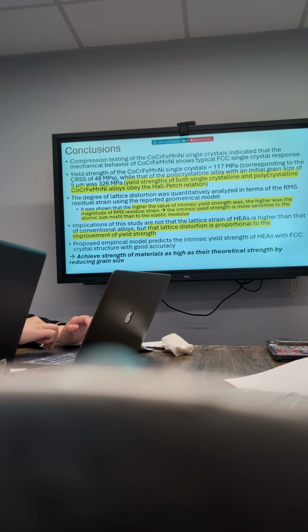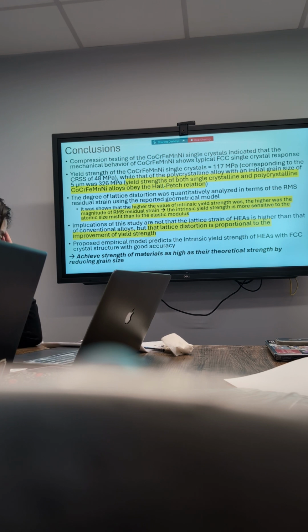The higher value of intrinsic yield strength. Oh, it was shown that the higher value of intrinsic yield strength found there was a higher magnitude of the root mean square residual strain, and so they found that the intrinsic yield strength is more sensitive to atomic size misfit than the elastic modulus is, which I think makes sense because intrinsic yield strength has more to do with the lattice mismatch versus the elastic modulus.